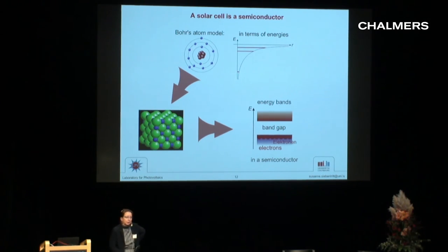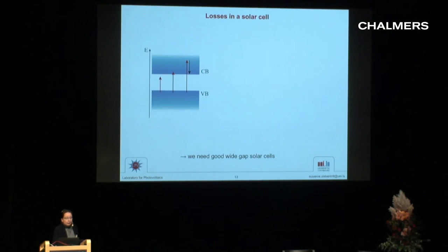And a semiconductor is a material where the band below the gap is filled with electrons, and the next band is completely empty. That means we first have to add energy to get a current, because nothing can move down here, it's all full, and nothing can move up here because it's empty. And this band gap is also the absorption edge, as Joseph has explained. You want it as small as possible to get a high current, and as high as possible to have a high voltage, so you have to find an optimum, which is a compromise between the two.